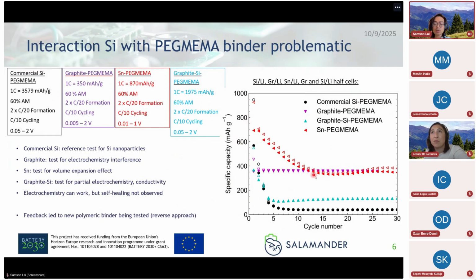And then when we do a graphite silicon test, maybe it's just electroconductivity. But in the end, we actually got performance basically proportional to the amount of graphite that we have. So flat, but lower based on that. So we kind of demonstrated through all this testing and a lot of failure, but we were able to see that the electrochemistry is working, but we're not able to really see the self-healing.